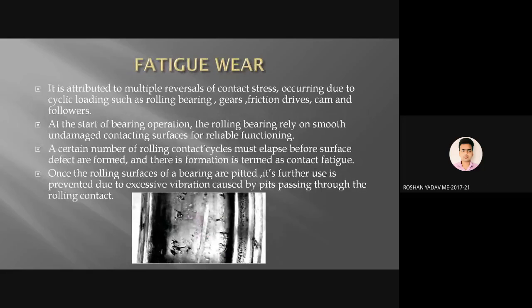Fatigue wear is attributed to multiple reversals of contact stresses occurring due to cyclic loading, such as in rolling bearings, gears, friction drives, cams, and followers. At the start of bearing operation, the rolling bearing relies on smooth, undamaged contacting surfaces for reliable functioning. A certain number of rolling contact cycles must elapse before surface defects are formed, in terms of contact fatigue. Once the rolling surfaces of a bearing are pitted, further use is prevented due to excessive vibration caused by pits passing through the rolling contact.